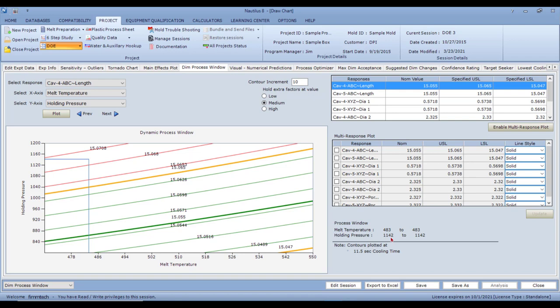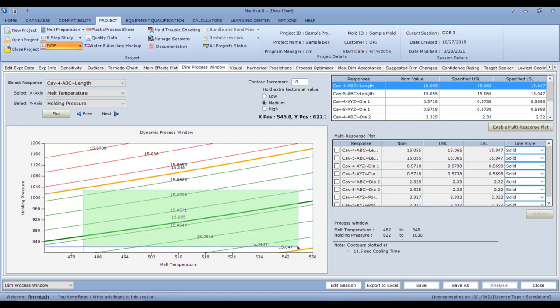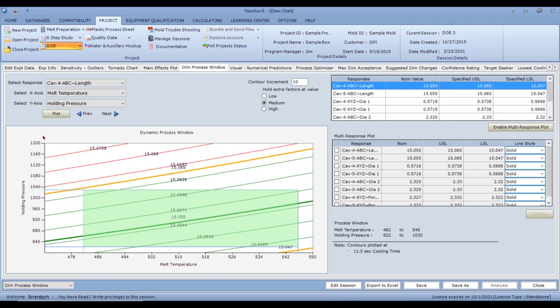At 483°F and 1,142 PSI you'd be out of spec. I can draw a process window and confidently say: if I set my process between 482°F and 546°F and a holding pressure between 822 and 1,030 PSI, leaving cooling time at 11.5 seconds, I'll always be within spec. This is the dimensional process window. The cosmetic process window was 800 to 1,200 PSI — below 800 you get short shots, above 1,200 you get flash.